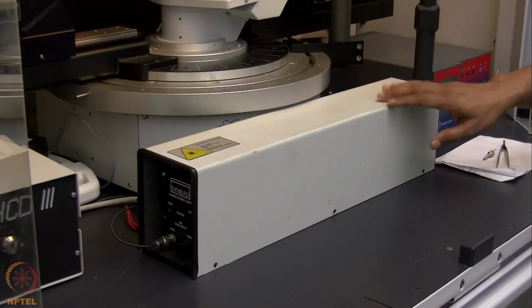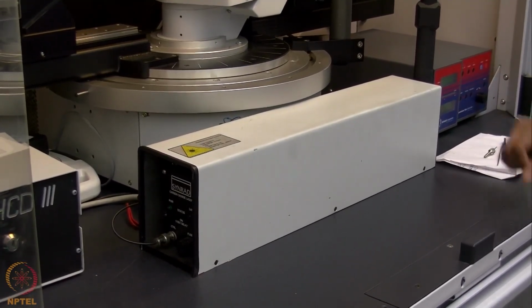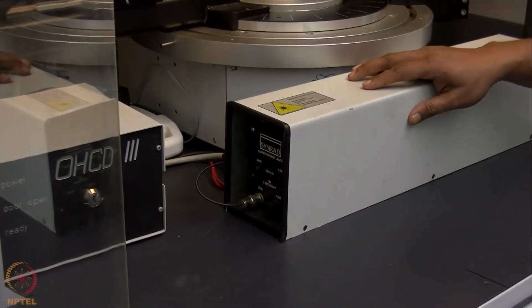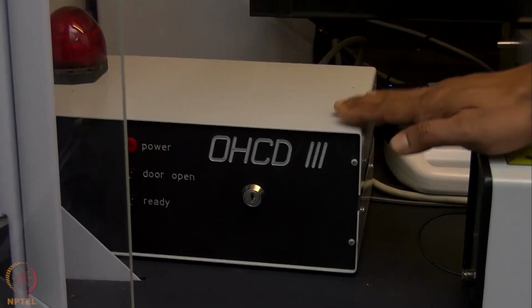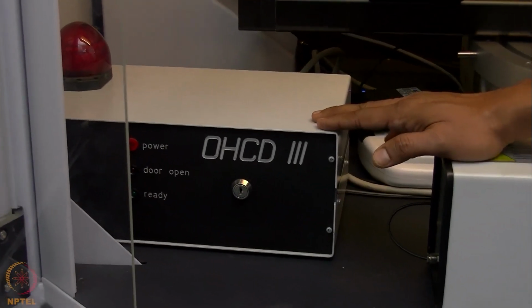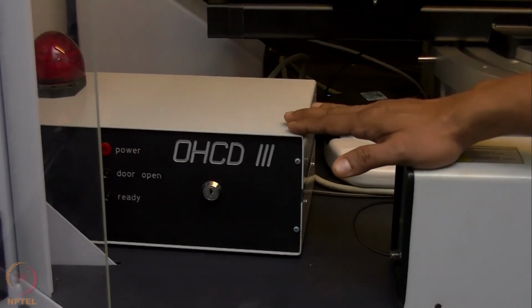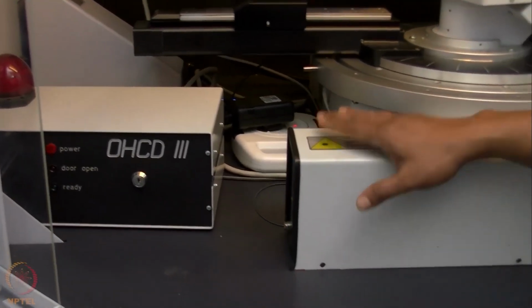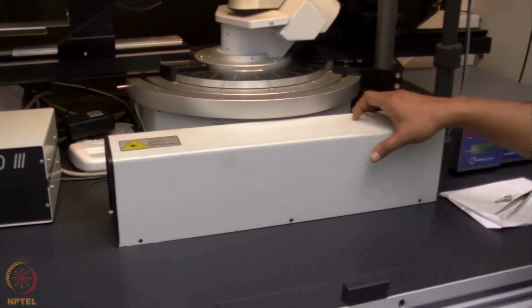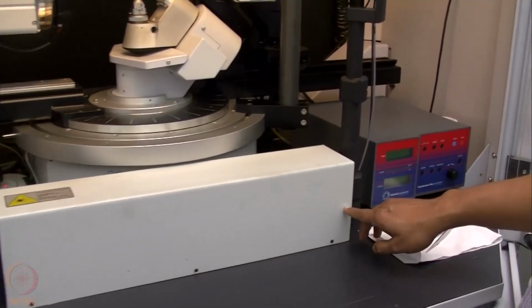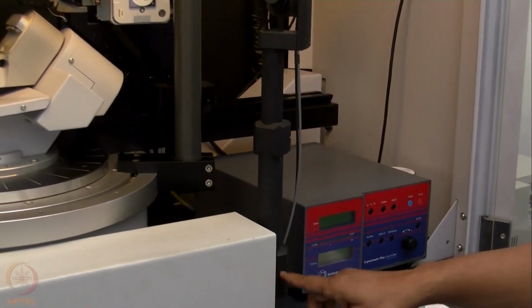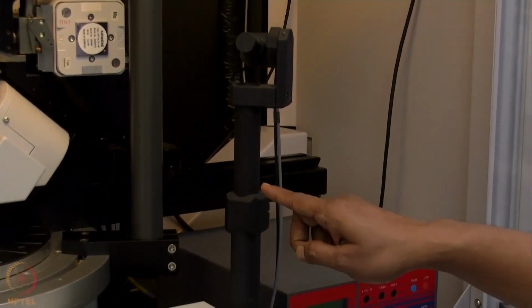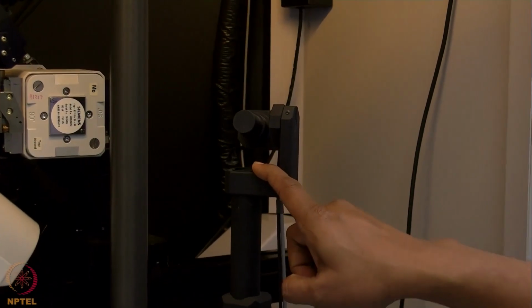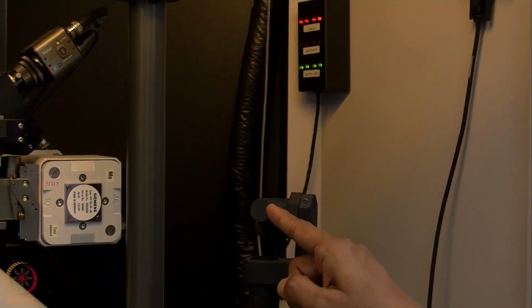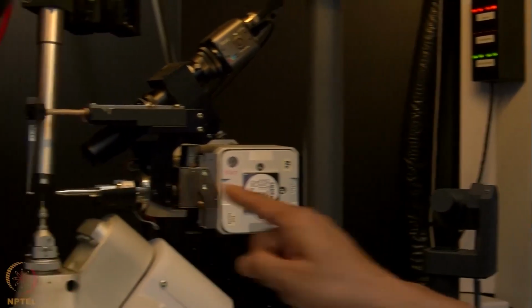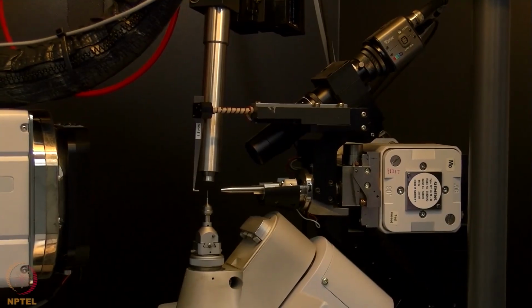So this is the setup of the optical heating and crystallization device, where we have one CO2 laser placed in front of the diffractometer here. This is the controller of the OHCD, which is then connected to the computer so that the voltage power supply to the laser is controlled, and then this laser is placed inside this cabinet. The CO2 laser comes in this direction, gets reflected from here, there is a mirror, and that reflected beam comes up, and again here it is converged, and then there is another mirror here which then reflects the CO2 laser towards the capillary of the in situ crystallization experiment.